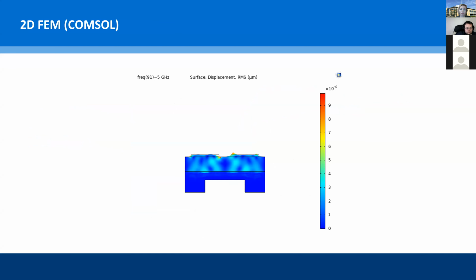You can see the two-dimensional model that we developed using COMSOL, and here we are showing the displacement profile. Once you activate the device, you can see the oscillations very clearly. The displacement that we got was in several picometers, which is better than the existing device, because in the existing device you get a displacement of several femtometers. So we get higher displacements. And the one main thing you can see is that most of the acoustic energy is constrained within the resonating structure, and you cannot see much loss.